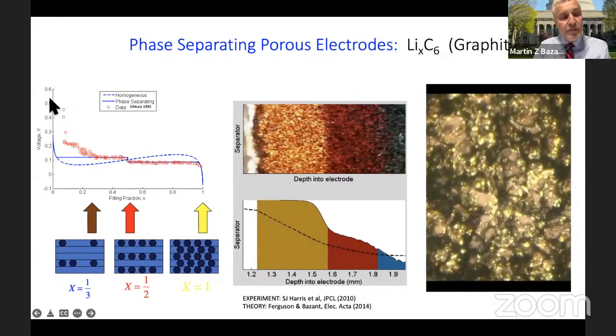So if I look at the voltage of lithium in graphite as a function of lithium content on the horizontal axis, we see plateaus like I showed you before, but instead of a single plateau like lithium iron phosphate, which corresponds to 2 stable phases at the endpoint, the voltage is a staircase, okay? And what that means is that at every end of one of these steps is a stable phase. And this is known. For graphite, it's known that there are many stable phases, and they correspond to different layers being filled of the structure and also various other patterns that could occur at lower concentrations.